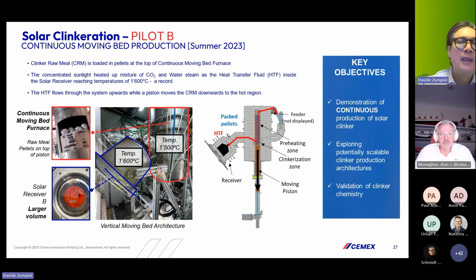So we actually had a continuous, vertical moving bed set up. It also speaks to the fact that maybe the production of clinker can be revisited. Maybe you don't have to use the conventional kiln that we're using today, but maybe a different way of heating up materials. So you can see in this second pilot, we were able to produce the clinker in a continuous way and achieve the clinker chemistry